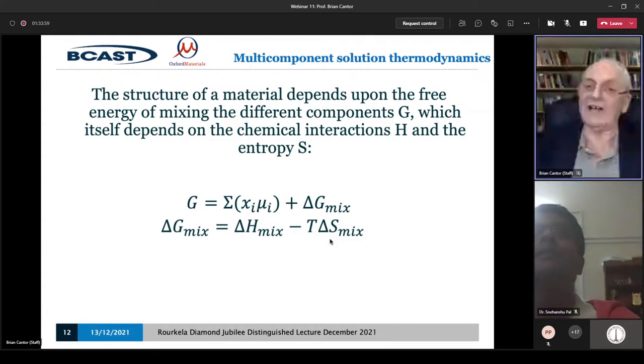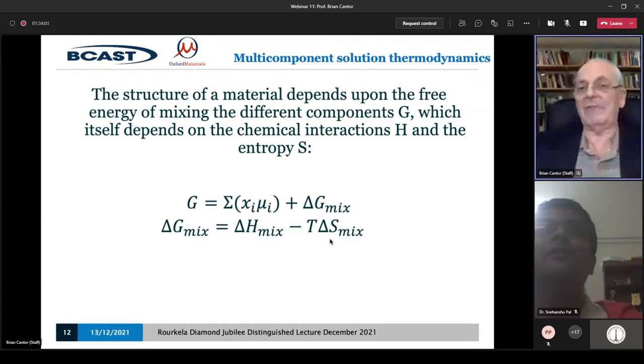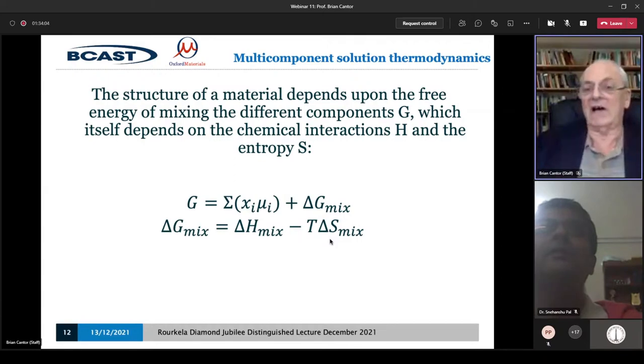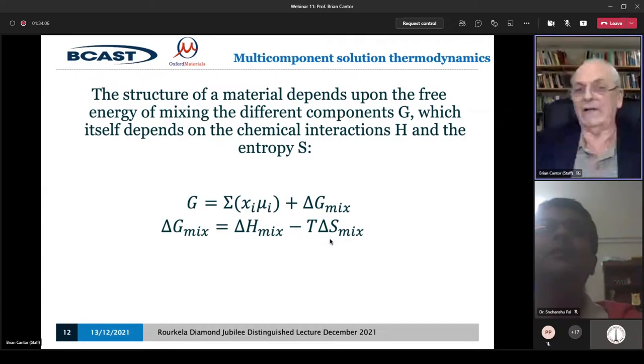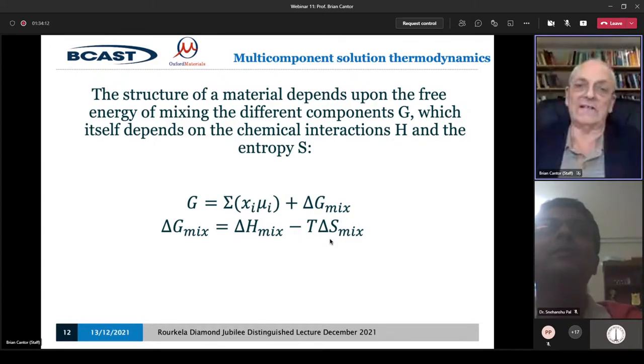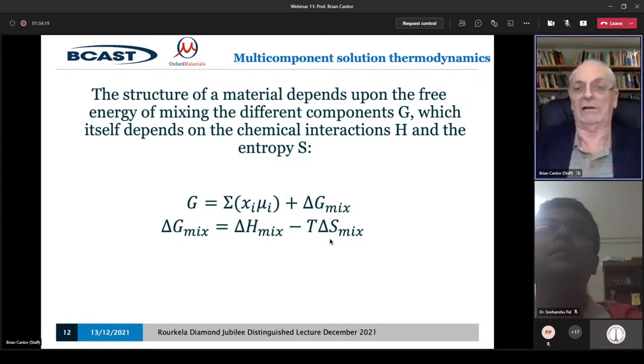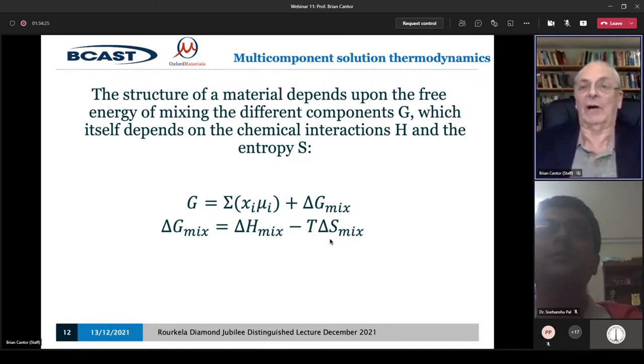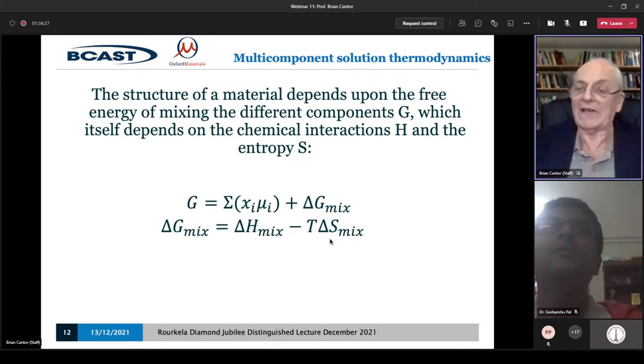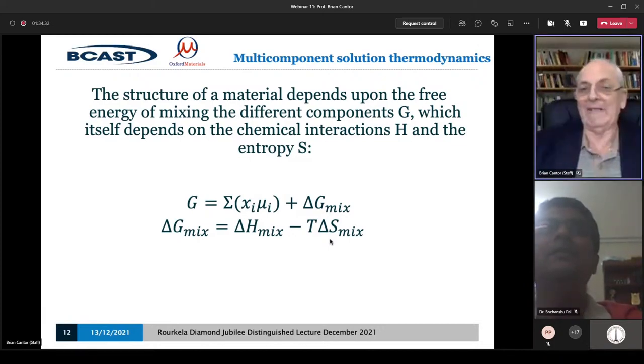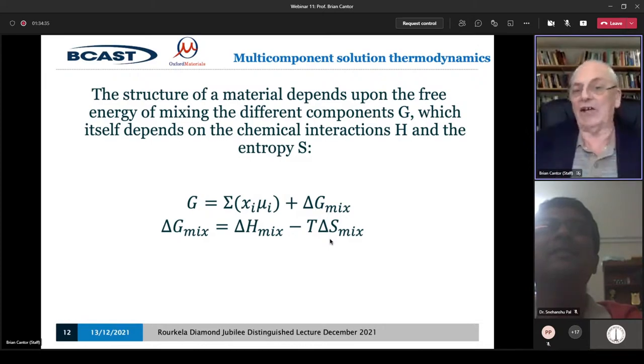And that's precisely, we make use of that already with all our steels. We make most of our things out of steel. Steel is iron and iron carbide, a mixture of iron with small amounts of iron carbide. Iron carbide is unstable. Cementite is not a stable compound. If you anneal steel for long enough, the cementite becomes carbon. The stable structure is pure iron and pure carbon. And at low temperatures, it must demix to pure iron and pure carbon, and the cementite compound becomes unstable. So the same effect occurs in these multi-component alloys.